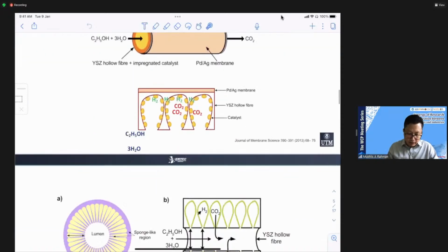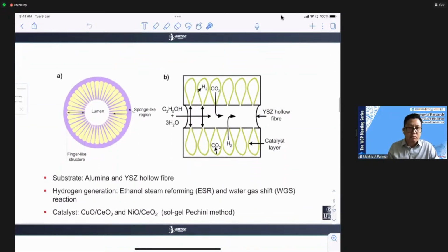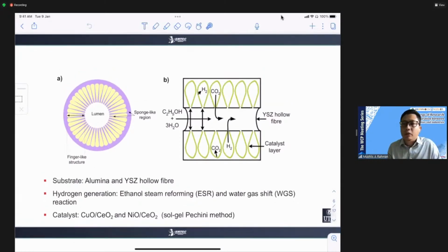So the first step is to investigate a number of ceramic membranes. In our work, we use alumina (aluminum oxide) hollow fiber and yttria-stabilized zirconia hollow fiber. Both membrane materials are sufficient, and because we want to perform the catalytic reaction inside the inner surface, we will use high purity ceramic material. Otherwise, these impurities will corrode our membrane and affect our chemical reaction.